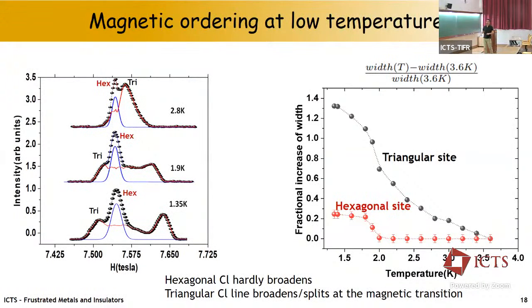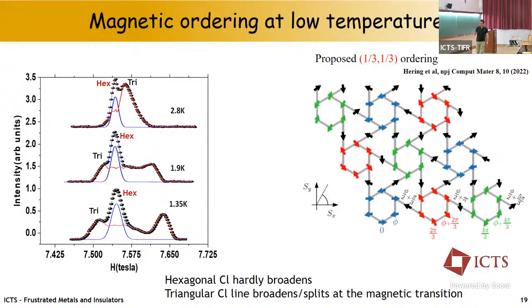We can try to compare with the spin texture that was proposed theoretically, which is a bit complex, but I'll go a bit fast. But now we have the perfect triangles. So the model is made in the limit where J prime equals 0. So there is one bond missing everywhere on the lattice. So on each perfect, so now we have three different perfect triangles, the blue, red, and green. But for the local probe, they are the same. Actually, it's the different orientation of the spins.